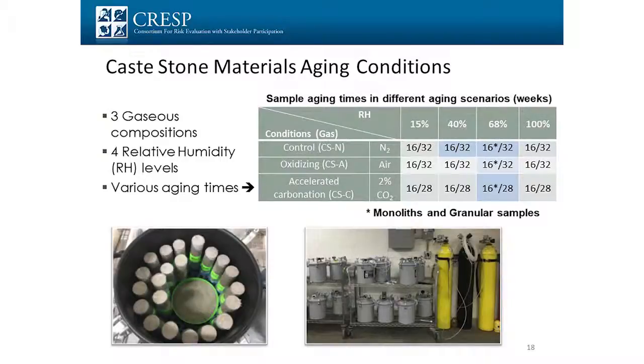We also looked at the saturation effects on these materials. So this is the second series of tests, where first we're looking at carbonation and oxidation, and we're also seeing how the saturation changes for these materials, because these high salt wastes really want to soak up water, but as you start reacting things, they also produce water, so you have to keep track of the water in these materials. A place like Savannah River, it's pretty much saturated. A place like Hanford, it's not saturated, so they're very different environments. So we're extending what we did for saltstone to the cast stone materials as well.